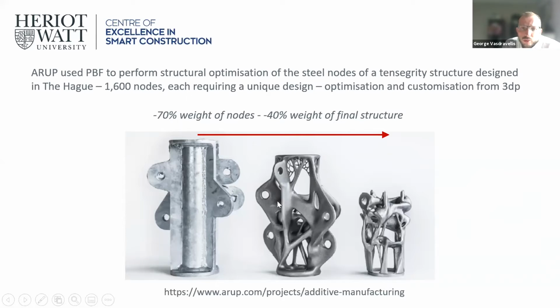The first iteration to optimize this node is here in the middle. The final node, the most optimized, if you like, is this one here. This was all 3D printed by the powder bed fusion technique, and this resulted in a 70% weight reduction of the node, and overall in a 40% weight reduction of the final structure.